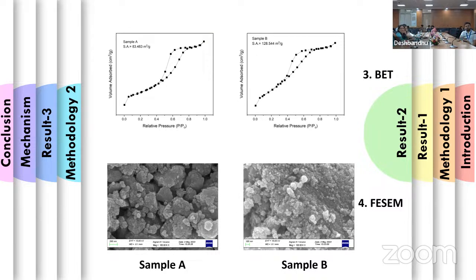This is the BET graph, and both the graphs represent a type 4 isotherm with an H2 type curve, which depicts the presence of ink bottle shaped pores. These are the FESEM images, which show agglomerated particles, but the particles are of spherical shape.